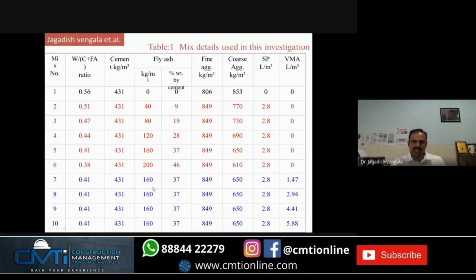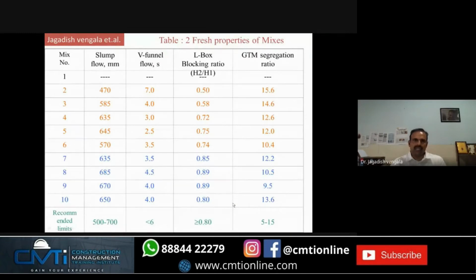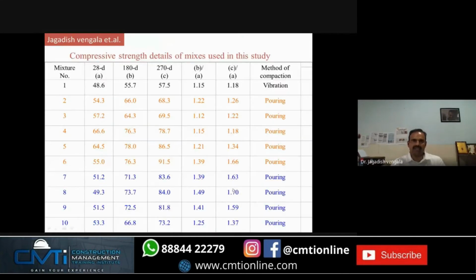So for 30, 160 or fly ash, and then fine and coarse aggregate values. Coarse aggregate is less when compared with the fine aggregate, you can see here. These are the slump flow, V funnel and L box. Here you can see 7, 8, 9, 10. We have taken it for the final mixes. Here you can see V funnel is satisfying, L box is satisfying, GTM segregation ratio is satisfying.